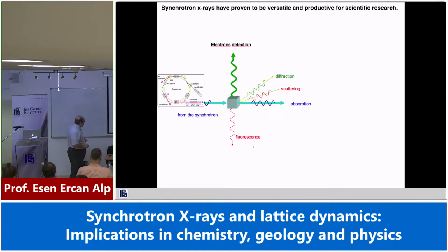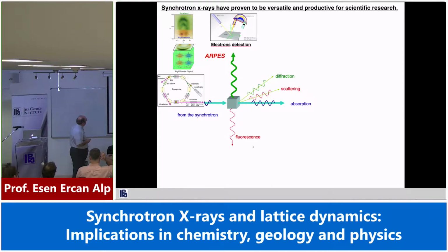So you can say, give us an example. I will give you a few examples. For example, if you take this electron detection and send it to a hemispherical electron analyzer, which is something all ESCA machines in your labs have, you can then take a single crystal, measure along certain crystallographic directions, and you will find that angle-resolved photoemission spectroscopy will give you the Fermi surface.